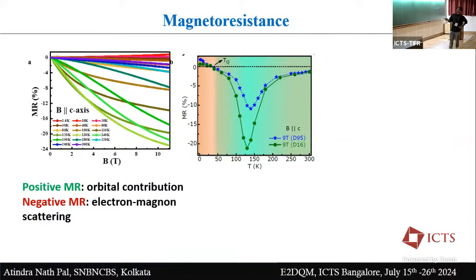So with the magnetoresistance data, you also observe a very interesting observation. If you plot the magnetoresistance from the two devices, you see the magnetoresistance is predominantly negative in this system, except below 40 Kelvin. Below 40 Kelvin, magnetoresistance becomes positive. But above this 40 Kelvin, you see magnetoresistance is maximum near the spin reorientation transition.